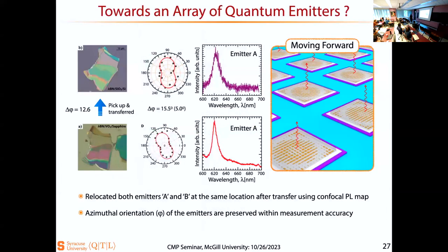One question which was very obvious to us was, okay, we found a color center and localized it in VO2, but VO2 is not a typical device substrate. VO2 has its own advantages, but a typical device substrate is silicon or SiO2. So can we pick it up and transfer it to a silicon substrate? The answer is yes. This is what we did. This is the same substrate, this is hBN on VO2 on sapphire. We picked it up.